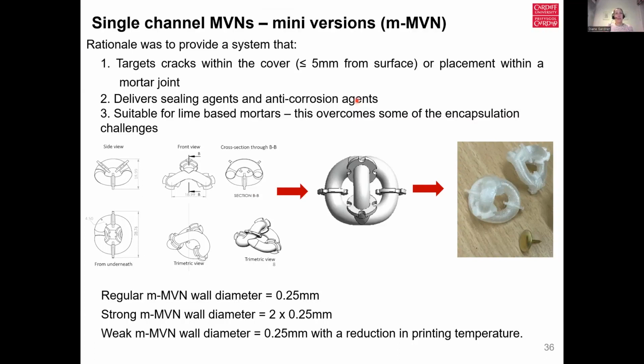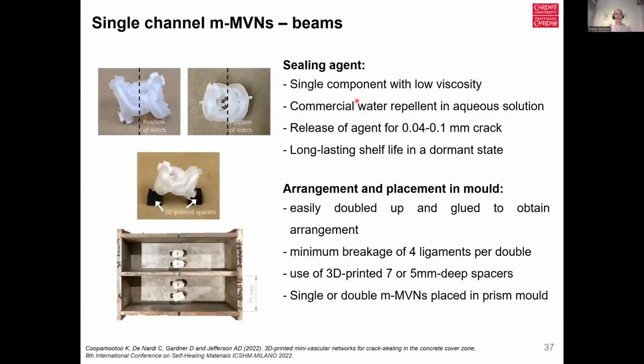And what we did is we just tried a few trials to begin with, looking at placing these in beams, so actually creating sort of combinations of these. So we actually double them up together. We place them on different printed spaces, whether they're 5mm or 7mm spaces, and we filled them with just general ink or a sealing solution, just to see if we can get things actually released out of these. So they release agent between, say, 0.04 to 0.1mm cracks, so they're working within the range that we want them to work. We need to break about 4 ligaments for each double combination to get flow coming out.